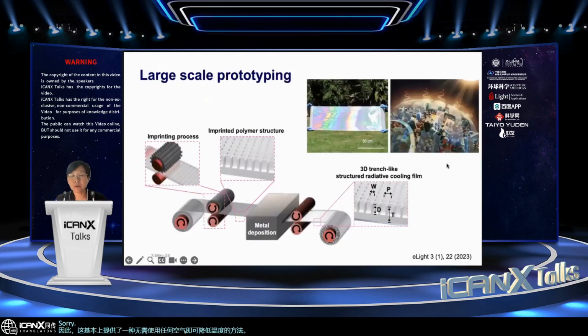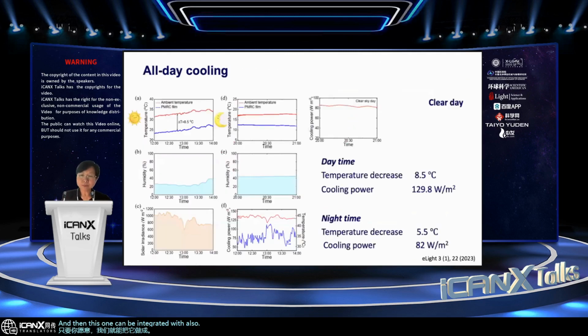Thinking about how to scale up, because it's a periodic structure, we use the laser to help us fabricate a mold. After we have the mold, we can use this roll-to-roll method to make that into large scale. In this case, you see that it's very colorful because the nanostructure is diffracting the light. And we can make that as long as you want.